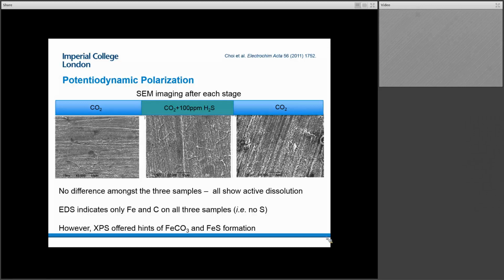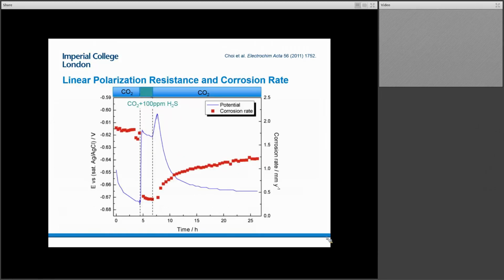But in fact, further inspection using XPS has highlighted that there might be some indications of formation of iron carbonate and iron sulfides. But this again points to the necessity that electrochemistry, even a very simple experiment, can help us understand quite clearly what might be happening. So it's an interesting way of viewing how much we can get from actually very limited and very simple experiments.